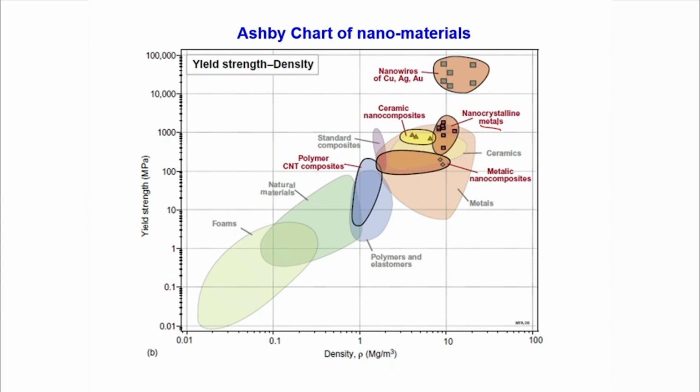At least I know about metallic glasses which can go up to 5 to 6 GPa yield strength. That is pretty large, but then you have very limited ductility. It fails miserably. On the other hand, these nanocrystalline metals may not fail miserably. They will have a certain amount of ductility which can be used. Okay, so that's something which you must remember. So this winds up our discussions on the mechanical behavior of material.